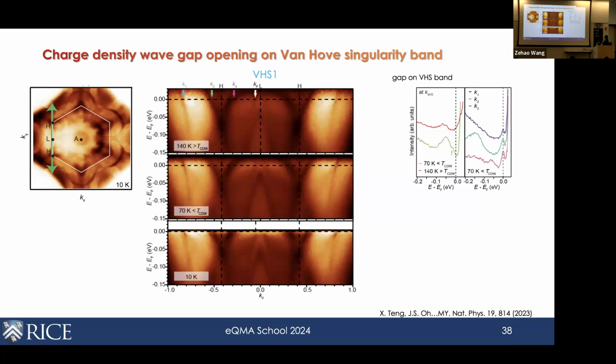We can look at how these bands participate in the CDW order. If we lower the temperature, with ARPES you can look at the spectral function at different momenta, and if you track the band at the Van Hove point, we actually see that if you go below the CDW order, there's a gap which develops on the Van Hove band. And this is not the case for the other bands that cross the Fermi level. And we can do a very careful temperature dependence, and you see that the spectral weight or the gap develops onsets roughly at the CDW order.